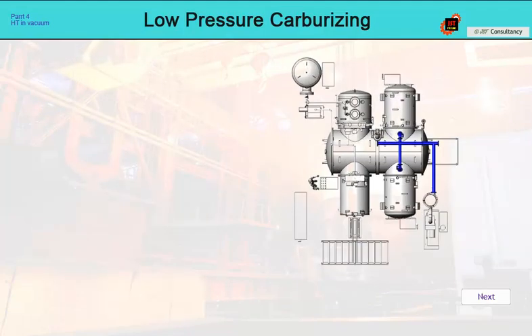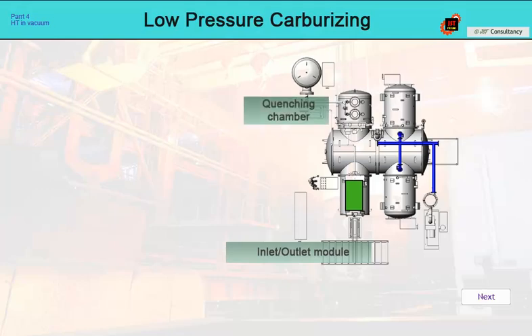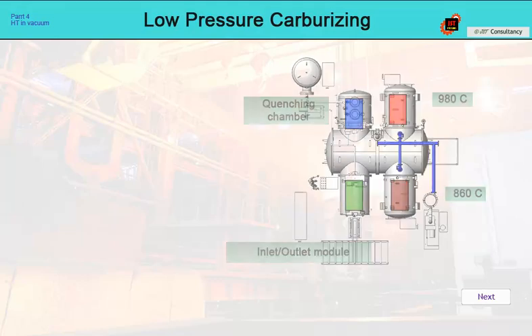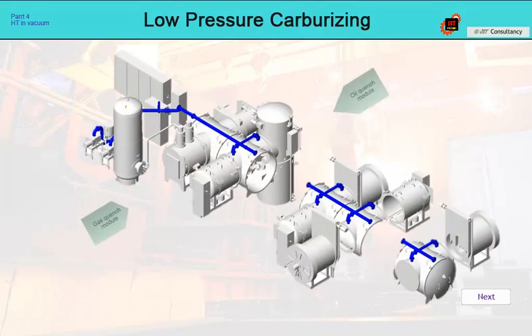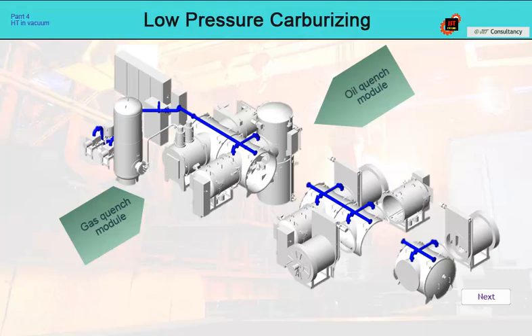This simplified model shows the ECM Flex device with an inlet and outlet module, 2 heating cells, and a quenching chamber with 20 bar of nitrogen or helium overpressure. In one chamber, we do the parts carburizing at 980 Celsius. In the other, we cool down the load to a quenching temperature of 860 C, and then we quench in a gas stream. The advantages and flexibility of this system are quite visible. Recently, so-called hybrid systems have also been developing rapidly, where we can have both quenching in oil and in a gas stream. This significantly increases our flexibility.